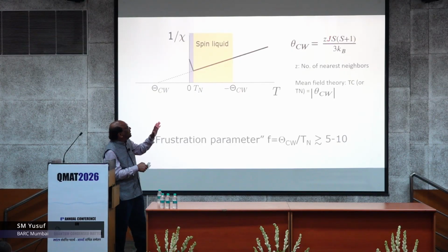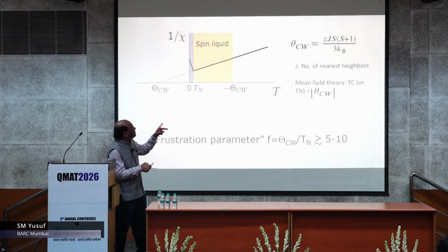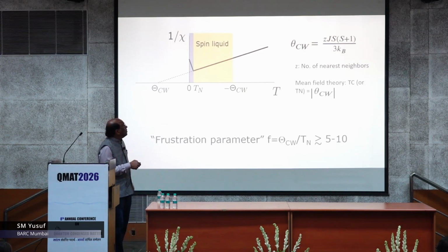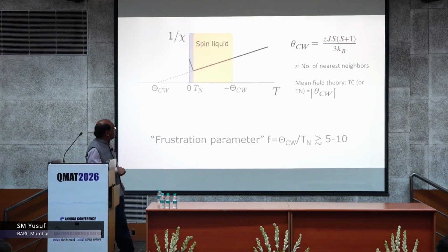Ideally, when this J is able to overcome kBT, the system should go for magnetic ordering. If that happens, then theta and TN are the same, that is the mean field. But if that does not happen, something else is playing a role, and that is the frustration. That is why this ratio is very, very important to measure, to see whether it is really deviating from 1 in a very big way.